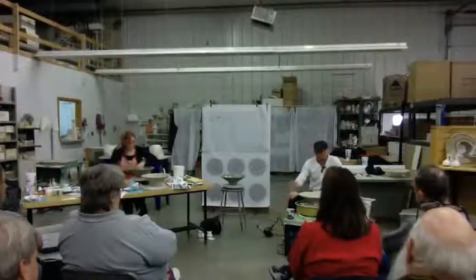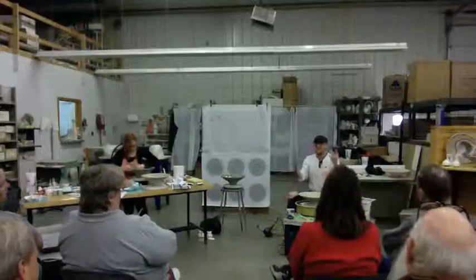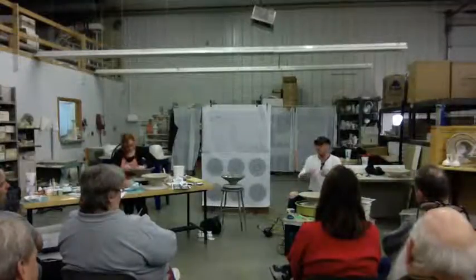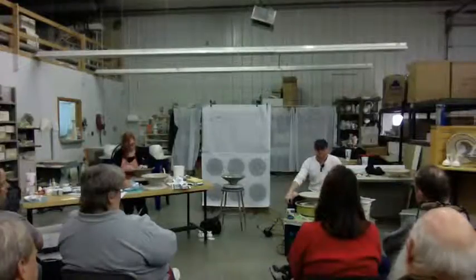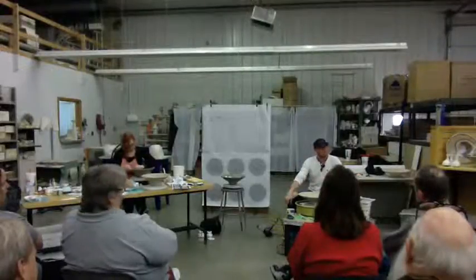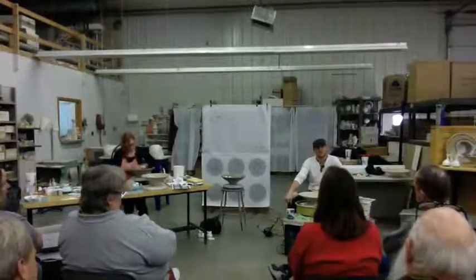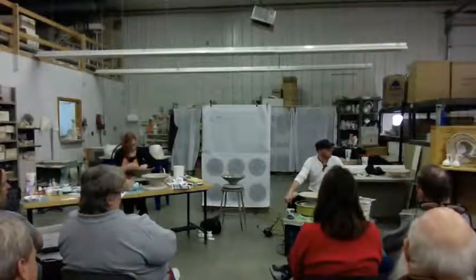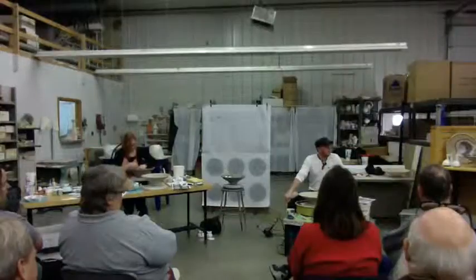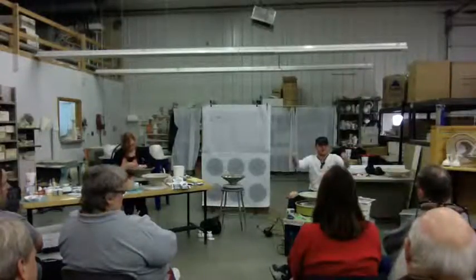Before I am impatient. Like, I pull this out, like this piece around the corner that's for the magazine, I pull it out, I'm like, it's awesome, it's beautiful, and I reduce it, 10 minutes later, I'm like, okay, let's take it off. But I usually wait 30 minutes before I take all of the trash cans off or the lids, and I don't clean with water. I do not clean with water. I get a wire brush, I scrape all of the paper off, and I only use 2 sheets of paper when I raku. I put one on the under and then one on top, and that's all I need.